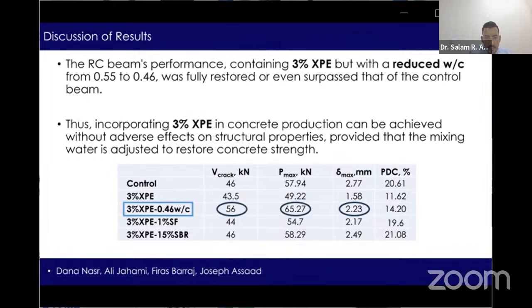From the previous figure representing the load versus midspan deflection plot, we can conclude that the performance of reinforced concrete beams with the addition of 3% XPE was fully restored or even surpassed the performance of the control beam when the water to cement ratio was reduced from 0.55 to 0.46. The corresponding values of V crack, Pmax, and delta max for the mix including 3% XPE and 0.46 water to cement ratio are the following: 56 kilonewton for V crack, 65.27 kilonewton for Pmax, and 2.23 millimeter for delta max. Thus, the disposal of 3% XPE plastic waste in concrete production can be achieved without negative effects on the structural properties, given that the mixing water is adjusted to restore the concrete strength.